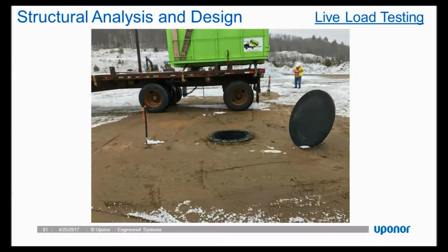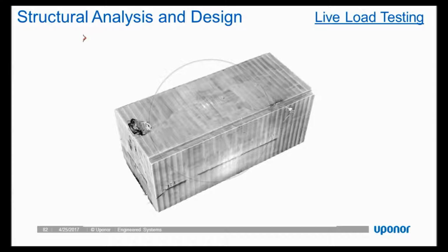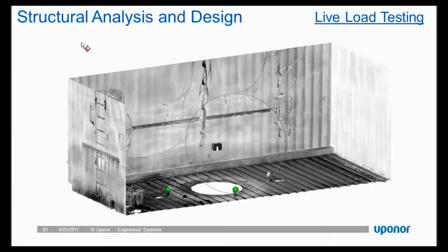So we simply fill up that bin with enough aggregate to get the axle load to the increment required, up to 32,000 pounds. Then we bring it to our location, we park it over the system, and we run our LiDAR scan, mark our point for pressure and strain, and allow the load to be applied for about a 15-minute total period of time to determine the deflection of the system and how the system performs. At the end of the day, here you can see a snapshot of our external LiDAR scan and then our internal LiDAR scan, along with some of the wiring and other equipment inside the structure.